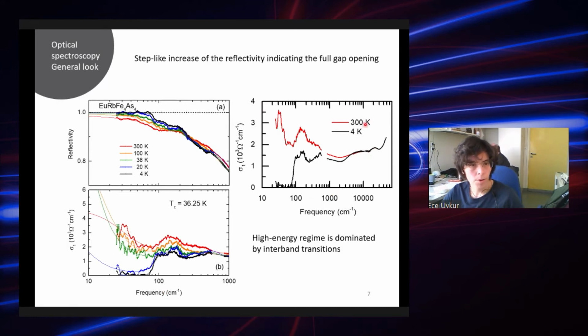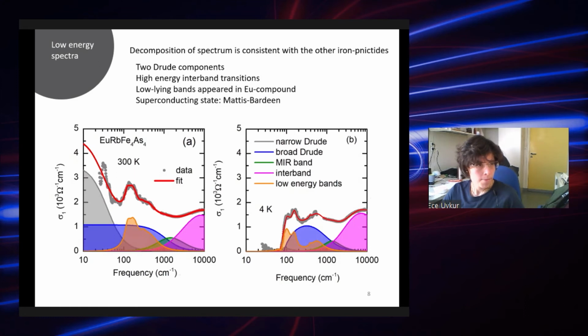I just plot here, at room temperature and in the superconducting state, the optical conductivity at high energies. There you see a couple of interband transitions that are pretty much temperature independent, and for the discussion of superconductivity and the europium ordering, this is certainly not very relevant at this point. Okay, then one can just go ahead and decompose the spectrum into different parts, which we try to follow, of course, from the other iron pnictide superconductors, which also quite nicely fit here.